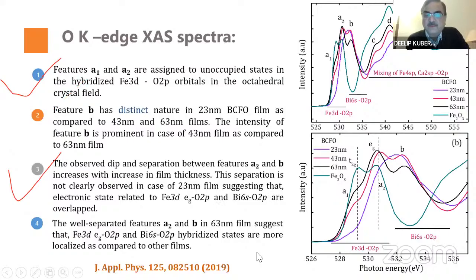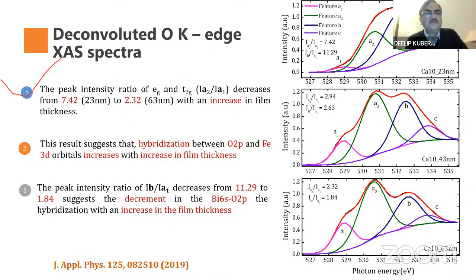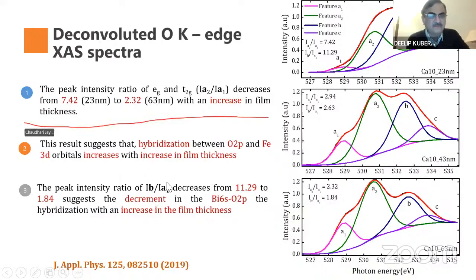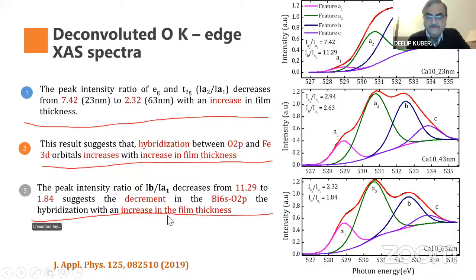So these are some of our observations after fitting the oxygen K-edge X-ray absorption spectra. Then we deconvoluted the oxygen K-edge absorption spectra, and we studied the peak intensity ratio between eg and t2g, the two different types of energy levels, which decreases from 7.42 to 2.32, from 23 to 63 nanometer, the highest thickness film, with the increase in the film thickness. What does this suggest? It suggests hybridization between oxygen 2p and Fe 3d orbitals.